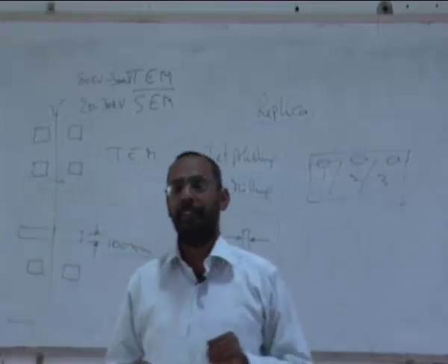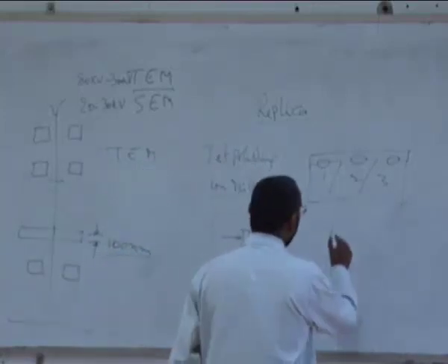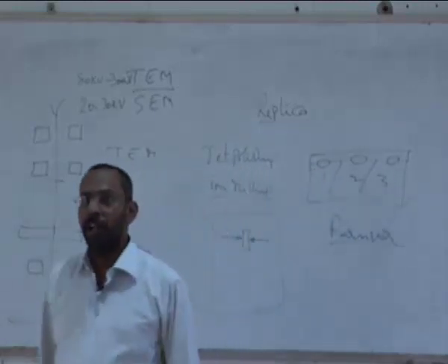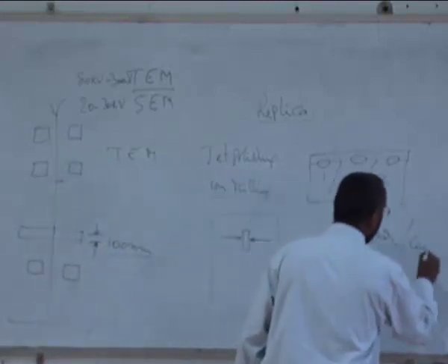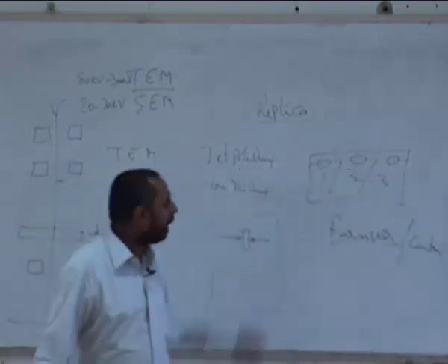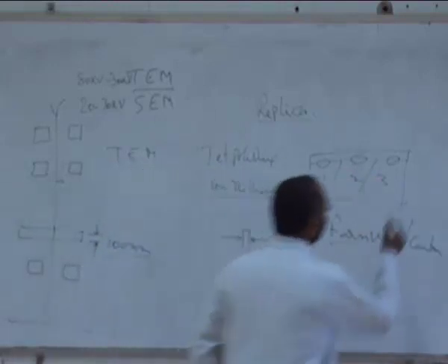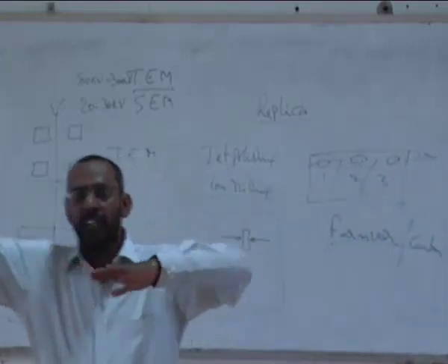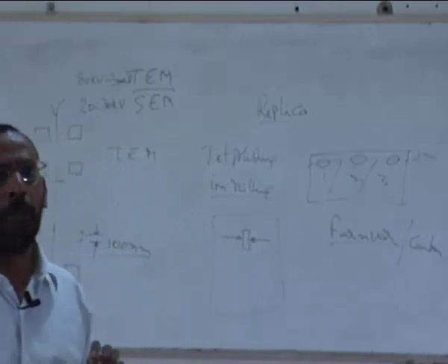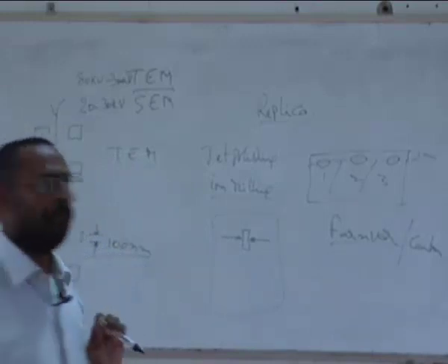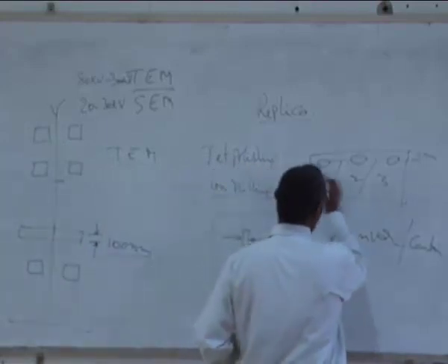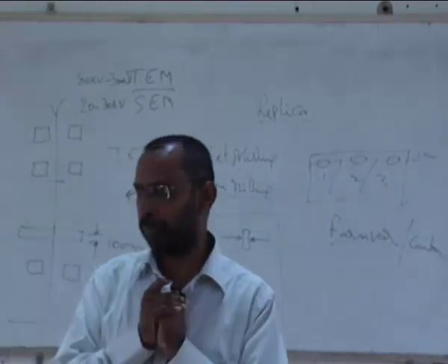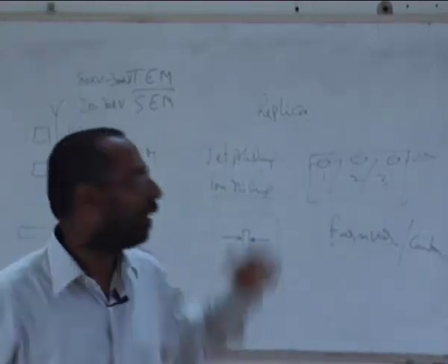carbon coating, or there are other polymer kind of materials called Formvar. Most commonly used is carbon or Formvar. This kind of thin coating, of the order of around a micron or 10 microns, is deposited on the surface, and then after it is deposited, it is just peeled off by some method. If you can put some kind of soap solution on the surface, so that there is not a very good contact between the two, it can be peeled off after the deposition has taken place.